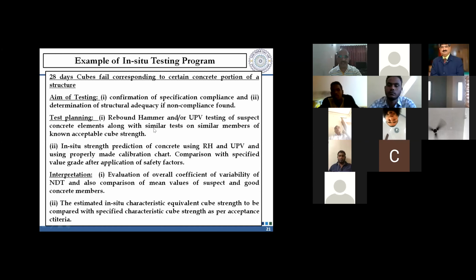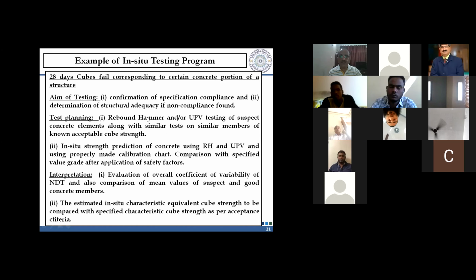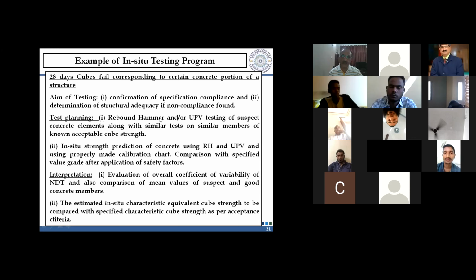For example, if I take the case of moisture content, in the rebound hammer you will get a lower value, while UPV will give a higher value. So if you perform both the tests together, use calibration, and make your assessment based on both, then the influence will be cancelled out. So you will get a better result. That is the reason rebound hammer and UPV are both performed over here.